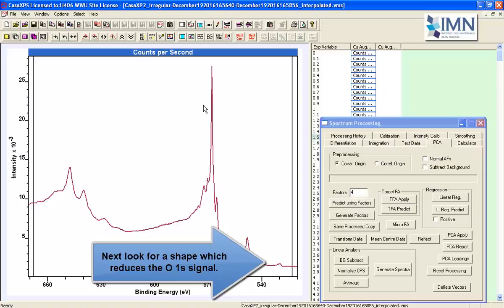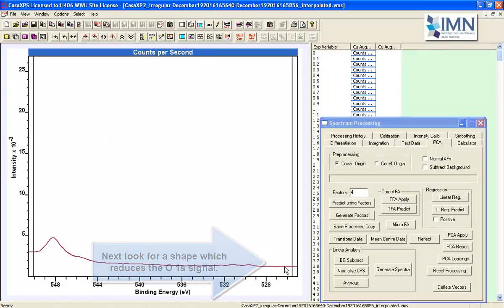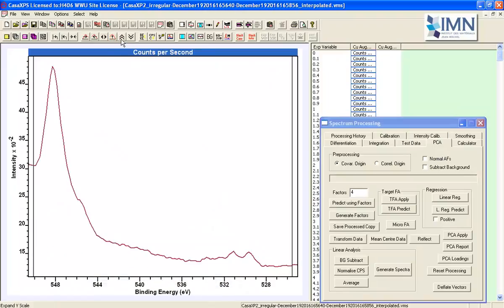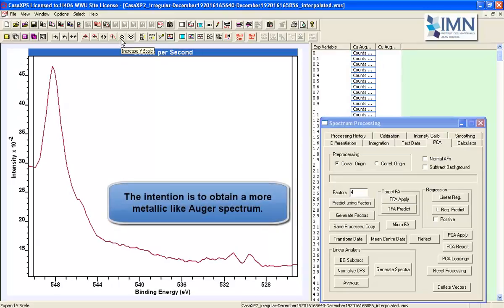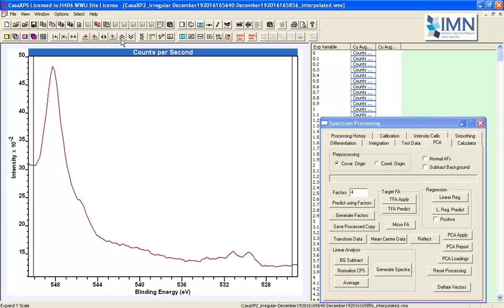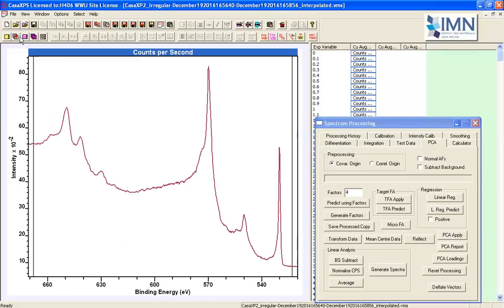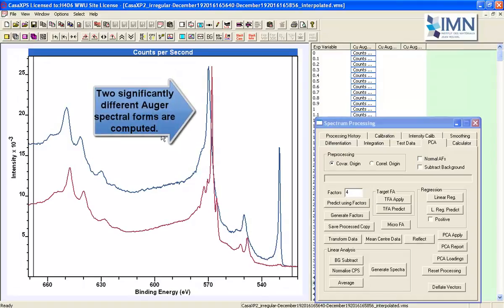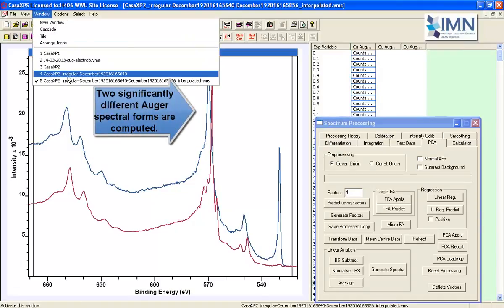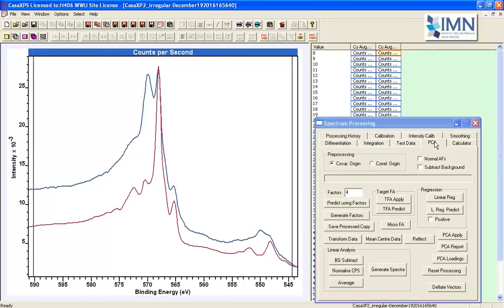Similarly, we can look for another shape where we try to reduce the influence of oxygen on the metallic form, because there should be no oxygen. Unfortunately, we can't actually remove the oxygen entirely — we don't have good enough overlap between the different oxides and the metallic form. So we're going to have to accept a little bit of oxygen, but we've been able to enhance the metallic shapes in the Auger lines. We'll save these two; you can already see quite different shapes for the metallic and the suboxide.